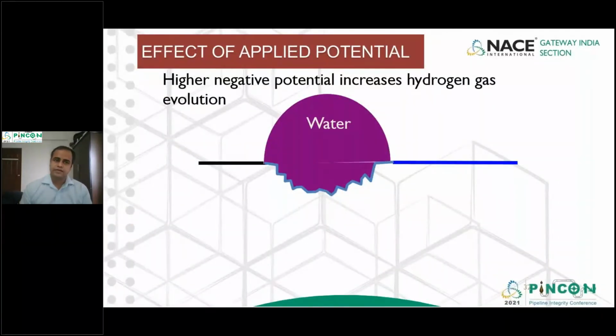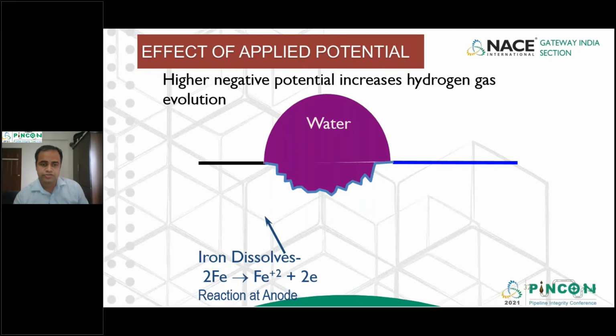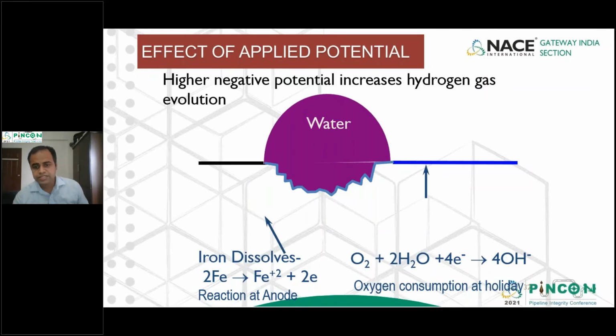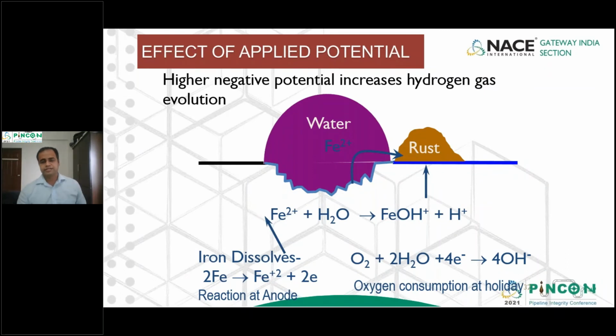Well, now what is happening? The higher negative potential increases the hydrogen gas evolution, which we are talking about, breaking down the adhesion between the coating and the pipe metal, because this hydrogen basically disbonds your coating from the pipe. So the iron dissolves as a reaction at the anode, and oxygen consumption happens at the holiday. And because of that oxygen consumption, what you get to see here is a rust hole. We should all be aware that Fe2+ plus H2O creates FeOH, which is a very well-known reaction, and the rust which is formed on the surface now is basically driven by the oxygen consumption at the holiday.